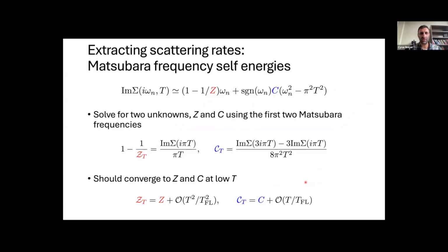Okay, so let's see now. Oh, sorry. One more thing I wanted to say was that I mentioned before this can also be done on the Matsubara frequency. Antoine and Fabian came up with this nice little procedure where if we take the same Fermi-Liquid scaling now in terms of Matsubara frequency, we have two unknowns. We have the quasi-particle renormalization and that C parameter. Therefore, we can fit this equation with two Matsubara frequencies, for example just using the two lowest Matsubara frequencies as we've done here, and get this curly Z and curly C, which can be shown to converge to Z and C as we go to low temperature.